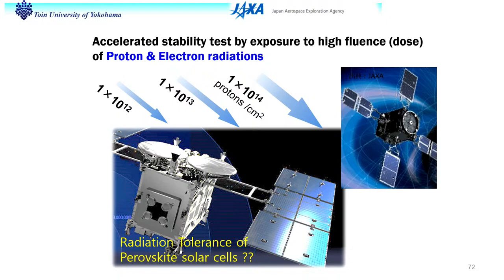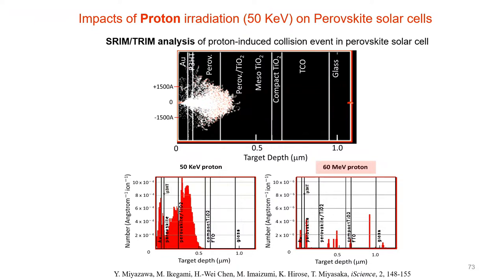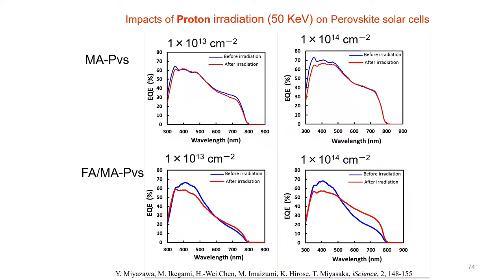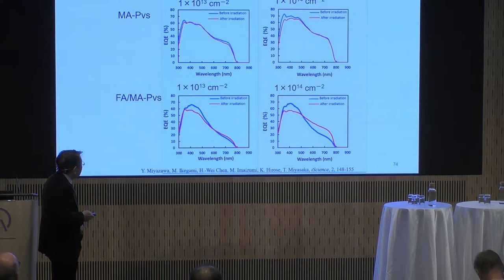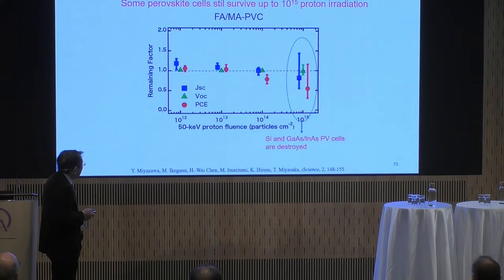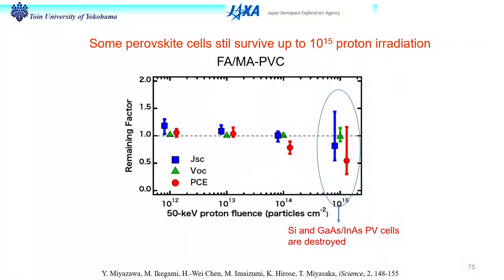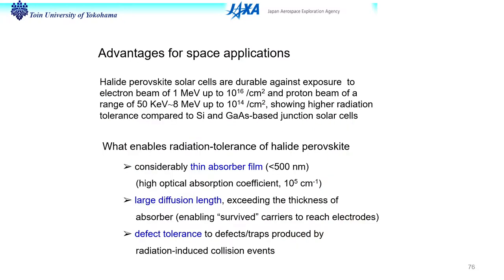Space applications are also very active in the world. We started there in Japan, and showed very high tolerance against high energy particle irradiation, like proton and electron. And this shows very high stability against proton irradiation, and 10 to the 15 dose of exposure of the device to the proton irradiation still makes the device survive. But at this level, the commercial gallium arsenide-based satellite device tends to be destroyed. Why? Because the absorber is very, very thin, and high energy particles can penetrate without stopping inside.